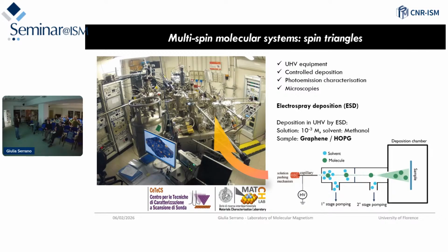So we can check also when we grow multiple layers, we can check the ratio between the signal that comes from the monolayer with respect to the rest, so we can control this. And then, when we really have to go to 200 nanometer thick films, we have dedicated chambers in which we can sublimate more. But most of the time we put this sample in air, because except for the titanium compound, all the other structures that I showed you are air compatible.